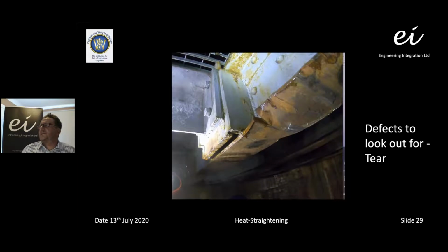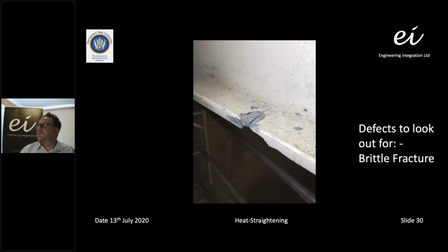Other aspects that we would need to look for whilst doing our inspections would be tears in the bottom flange, and also brittle fractures, where the impact has caused a brittle fracture. Obviously, we need to be aware of those, because if we start applying heat, we could exacerbate that problem. So we would probably have to cut that brittle fracture out, plate it before we started any heat straightening. So we're very conscious of any brittle fractures that occur in the steelwork in and around the impact point or remote from the impact point.